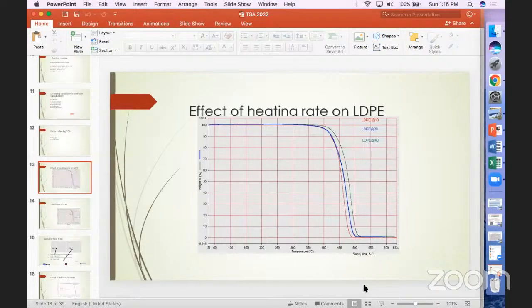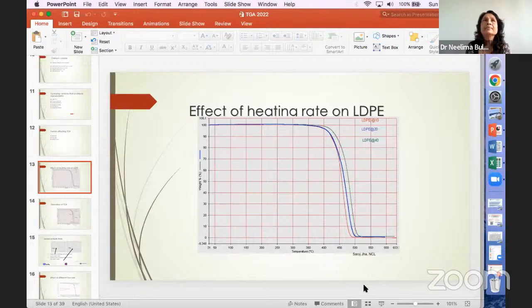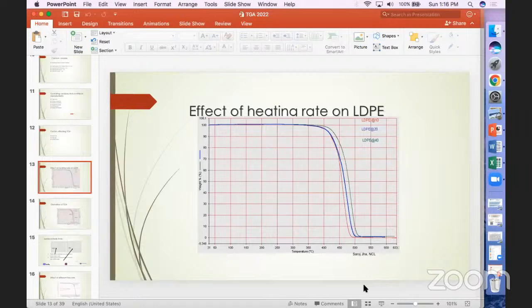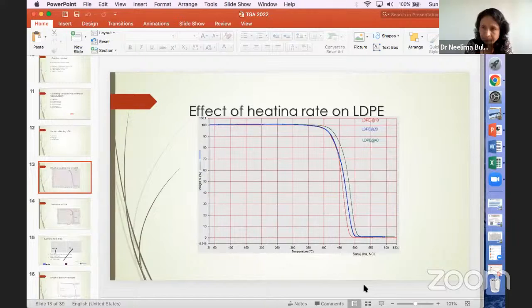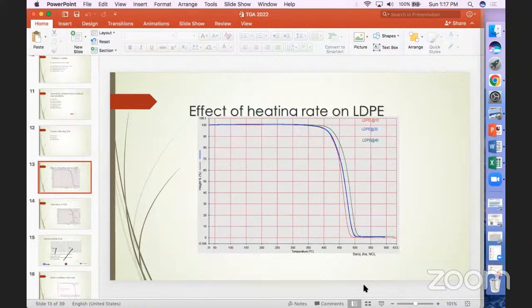Normally, suppose I have an unknown sample, either a thermoset or a thermoplastic, or a combination of both. I don't know whether it will have a Tg as well as an endotherm, and in the cooling cycle an exotherm and the related things. So how do I set the normal conditions? If I know the melting point, say for something like PTFE, I know the melting is so and so, the minus temperature is so and so, and the plus temperature so and so, then I can define it. So what do I do for that?